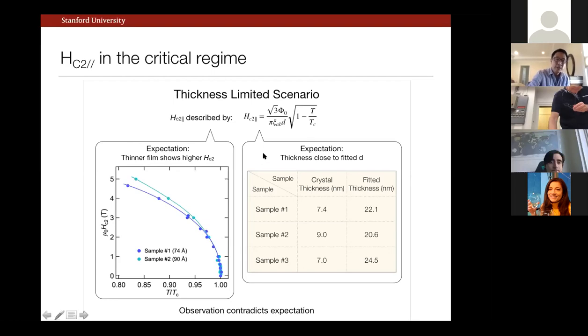So that's a scenario first discussed by Michael Tinkham, a case where you take, let's say, a three-dimensional superconductor, you make it very, very skinny such that you quench orbital motion for the in-plane direction, and it has, for the linearized Ginzburg-Landau form, a very simple functional form that gives you this characteristic square root of reduced temperature. And commensurate with that geometry, the two length scales involved are the in-plane coherence length and, in bulk, this would have been the out-of-plane coherence length, but in this case, it's the thickness cutoff of your geometry.